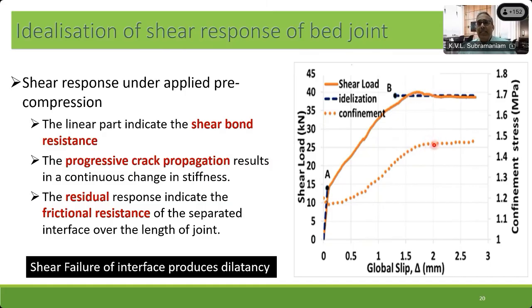up until a point when the load levels off and the confinement also levels off. So what's happening at this point? The crack has completely formed. Now, basically there is no bond. It's completely cracked. As the crack surfaces slip past each other, there's a constant amount of expansion that produces a constant amount of confinement in the system. At this point, the resistance is coming purely from frictional resistance between the two faces that are formed. Because the confinement is constant, the frictional resistance is also constant. So this is basically what's happening in a typical shear test.